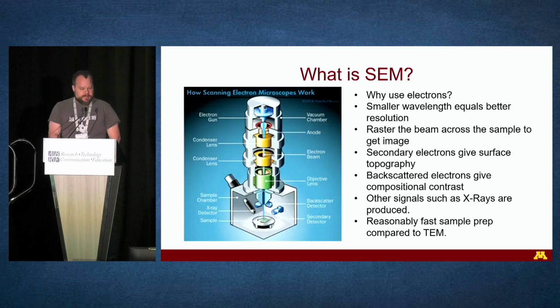So obviously, we can see we have a diagram of an SEM on the left. Why do we use electrons? Well, because we've got the smaller wavelength, and it allows you to get better resolution. In material science, people keep pushing to smaller and smaller scales, and we need smaller and smaller probes to actually visualize the materials that they're making. SEM is very useful in that we can raster the beam across a large area at very fine detail. We get the secondary electrons that give us our surface topography. We get backscattered electrons for compositional contrast. And then there are other signals such as X-rays for EDS. We can get diffraction for EBSD.